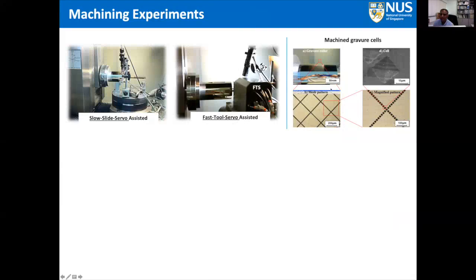being machined, and each roller consists of hundreds of lines like that, and each line has hundreds of dots. One of the dots is as shown here in this image, where you see multiple dots placed, and if you zoom into just one particular dot, it is something like this, where you can see that the average length in this case is about 10 microns in this particular image.